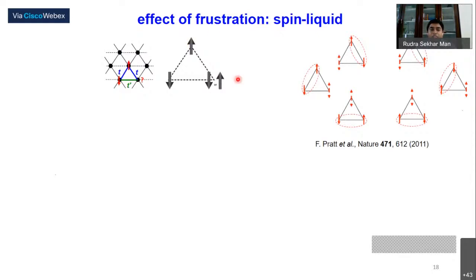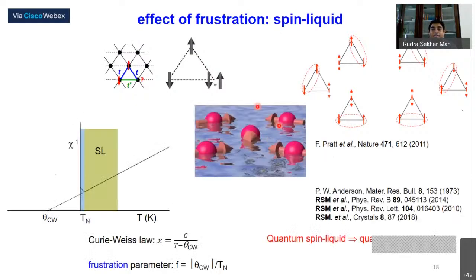And when these kinds of frustration appear, the spin somehow behaves like a liquid phase. It's called spin liquid, which I won't go into in great detail here, as I mentioned. One can think of this as a cover page from a Nature paper from Oxford that I have taken. There you see the spins are somehow different, one up and one down. Although we are measuring a solid material, because it's condensed matter, the spins somehow behave like a liquid, a kind of disordered phase, because the system doesn't know what the real ground state should be.